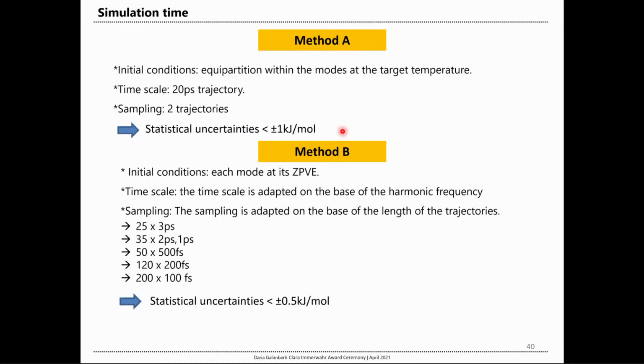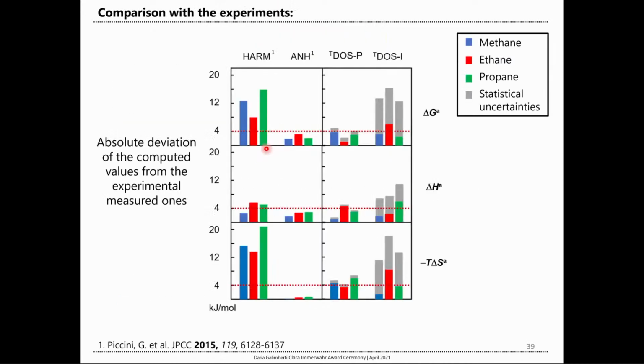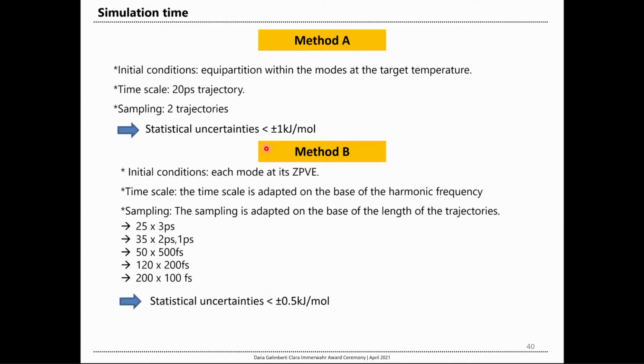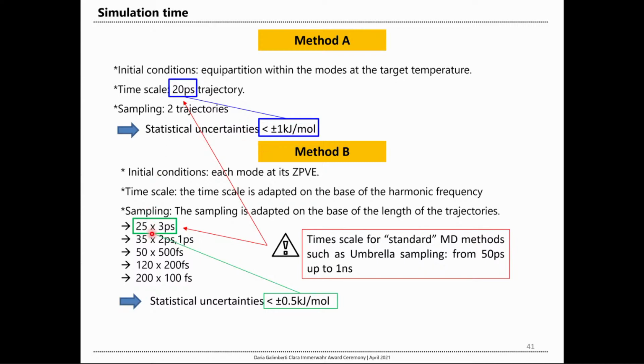So I don't want to go into detail on this. I only want to say quickly that, so far, I have shown you data using trajectories of 20 picoseconds. We also have a way that allows us to reduce the maximum length of a trajectory to 3 picoseconds. And remember that these 20 and 3 picoseconds have to be compared to the standard 50 picosecond to 1 nanosecond trajectories that are usually required.